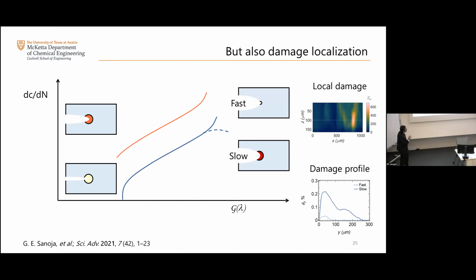In reality, the situation is slightly more complex, and I unfortunately don't have time to talk about it today because I want to get to something else. But I'm happy to discuss further if you are interested. Effectively, what we see is that at very large deformations, you can access a regime where your fracture is really catastrophic and really fast, but the damage is very low and very highly localized. So I'm happy to discuss this further later, but basically it's a little bit more complicated. It's not only about the magnitude of the damage, it's also about the localization in terms of a characteristic length scale ahead of that crack tip over which that damage is concentrated. Yeah.